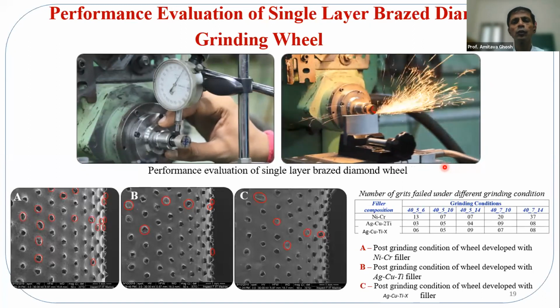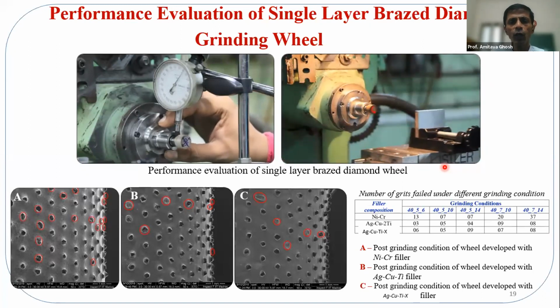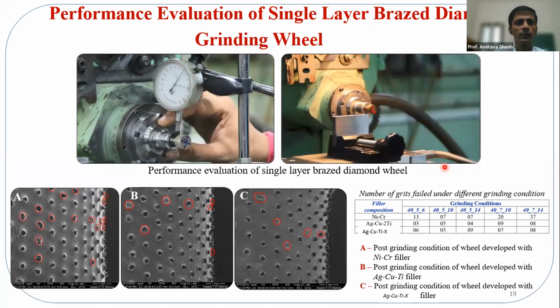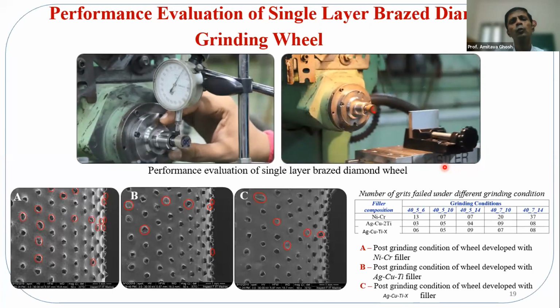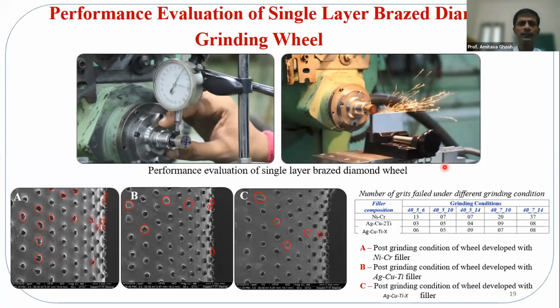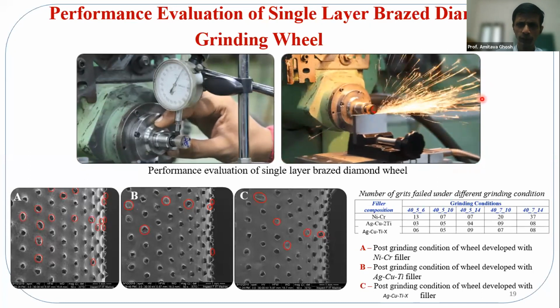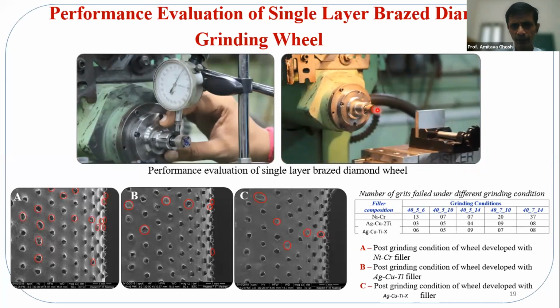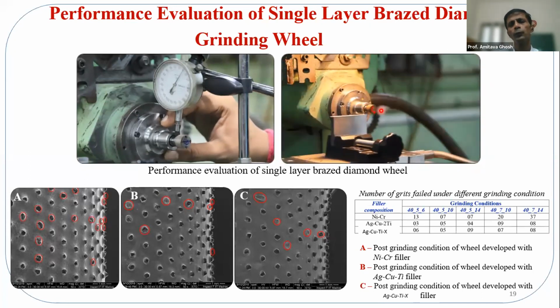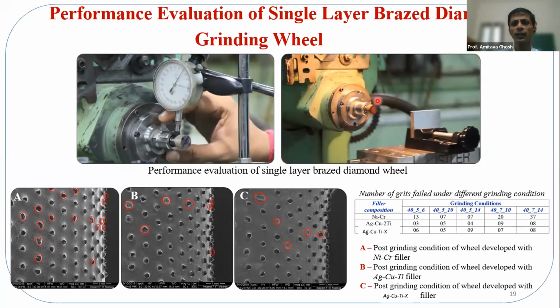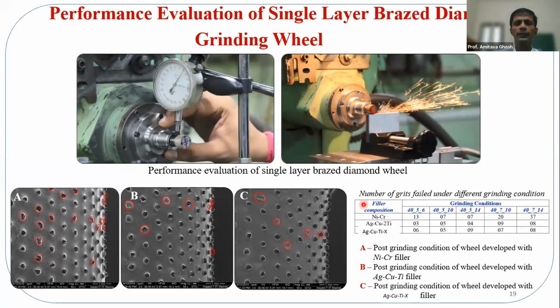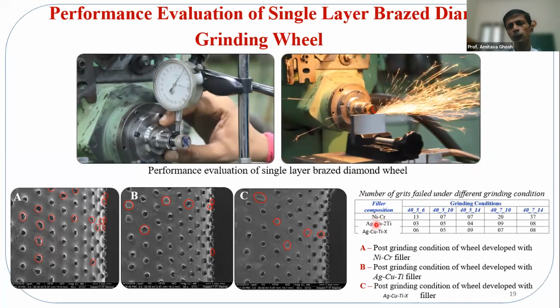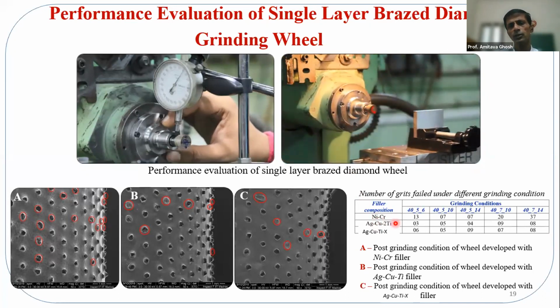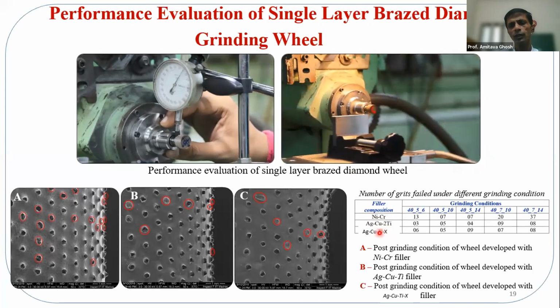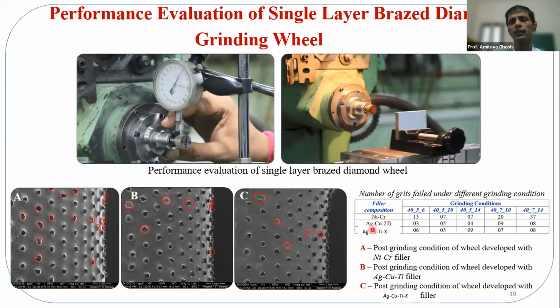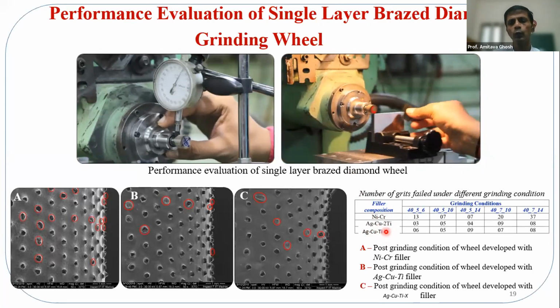If we replace the nickel chromium, that hard filler alloy, by a softer matrix like silver, the tool life improves quite a few folds. And these tools are also supposed to rotate at high RPM, and this technology is quite capable of withstanding all those issues related to high-speed grinding. Now, as I said, we compared the performance of nickel chromium, silver copper titanium, and the Ag-Cu-Ti-X matrix. This is a patented composition, so we didn't disclose much detail.